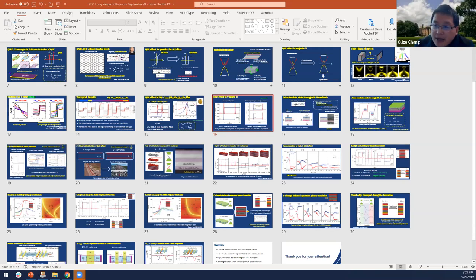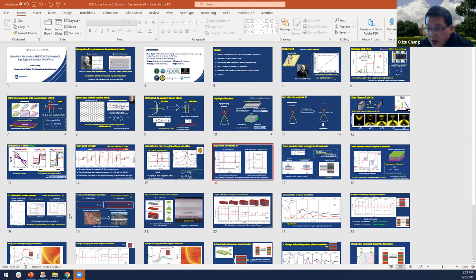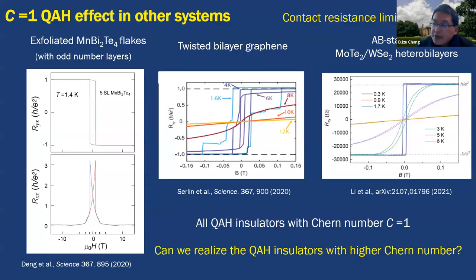As I just showed here, there are several of these in the quantum anomalous Hall regime. In the quantum anomalous Hall field, the definition of the critical temperature is pretty messy. For some systems they say one Kelvin, for some milli-Kelvin, but the criteria are different. If you use a similar criterion, in my opinion the critical temperature should be quite similar. For example, if we define the critical temperature as this ratio equal to one, or if we define the criterion as 97%, 98% or 99%, the critical temperature, in intrinsic magnetic topological insulators, in magnetically doped ones, and also in twisted systems, should be quite similar.